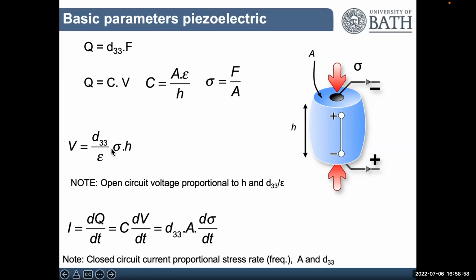So it's proportional to the stress, it's proportional to the height, and also it's proportional to these properties, D33, charge per unit force, divided by the permittivity. And this is interesting because obviously we need a certain potential to drive a reaction, or we also need a high potential to develop a good sensor. And the voltage is proportional to the height. And remember, it's the surface charge that you're collecting or you're using, and the voltage goes up with thickness because you're pulling those surface charges further away. So you're getting a bigger potential.